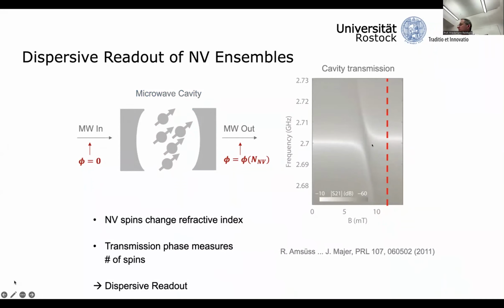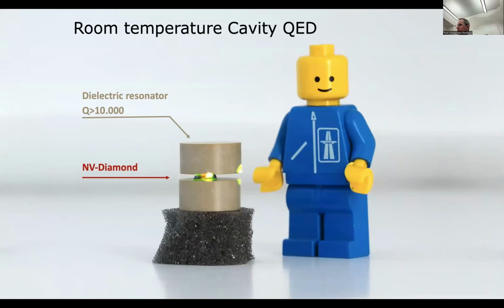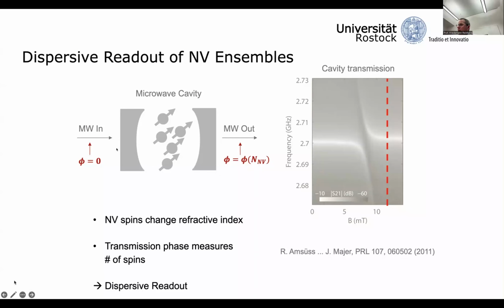For example, if we place ourselves in a region where the NV spins are fairly detuned from the cavity resonance, if you look very carefully, this white line still does not fully coincide with the naked cavity resonance, which would be somewhere around here. So the presence of these NV spins slightly shifts the cavity resonance, and this can be seen as a change in the phase of a transmitted microwave signal. This can also be understood in a physical picture. The NV centers have a strong index of refraction in the microwave range due to the proximity to this ground state spin transition. So they effectively shorten or lengthen a microwave cavity, and they can imprint on a transmitted phase. And with this approach, it actually is possible to read out the state of the NV spins.